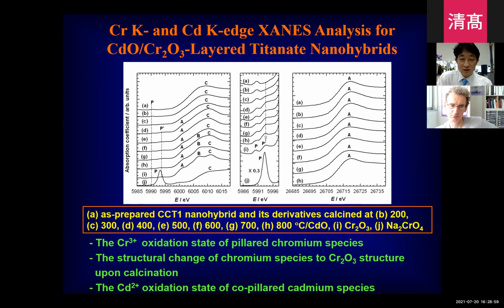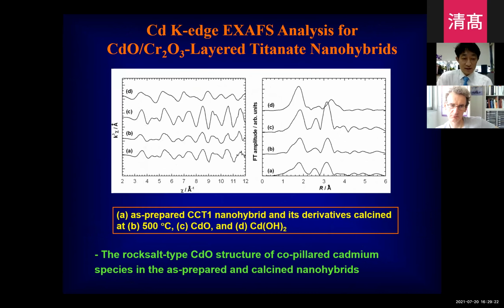We observe a distinct change in the pre-edge spectrum. But in the case of cadmium, the cadmium K-edge normally shows featureless, broad spectral features. So from that, it is not easy to specify the local structure of cadmium from the XANES analysis. So we did the EXAFS analysis, as you can see here. This is the reference spectrum and the calcined sample at 500 degrees. There's no significant structural change, so it shows the high thermal stability of the cadmium oxide nanoclusters. The FT feature is very similar to the reference spectra of cadmium oxide. It is strong evidence for the stabilization of rock-salt type CdO structures.